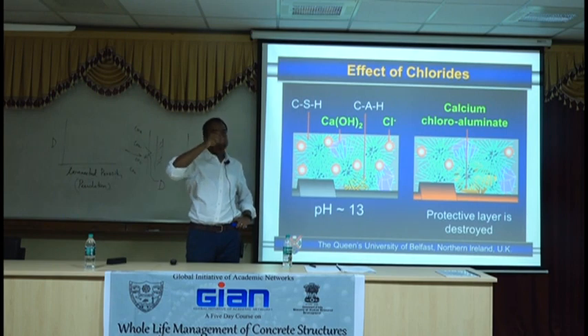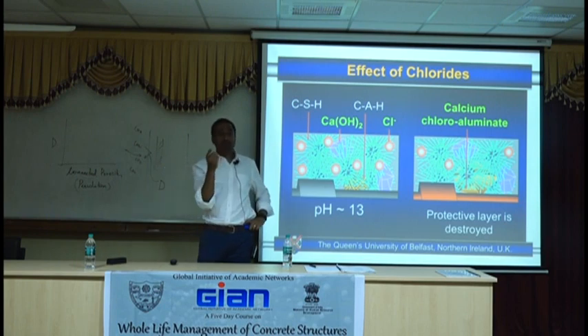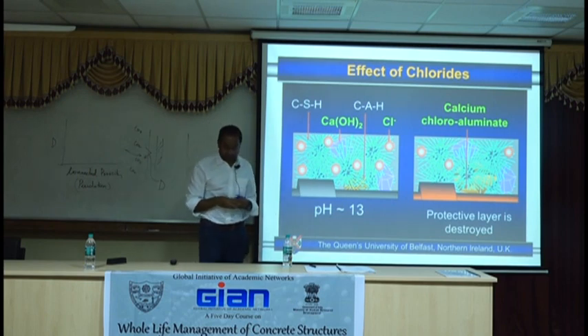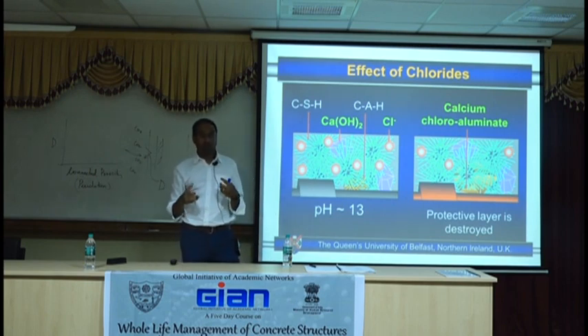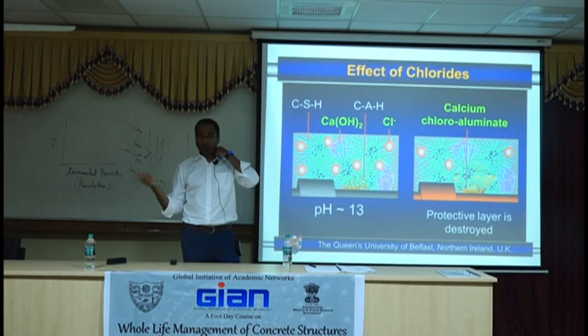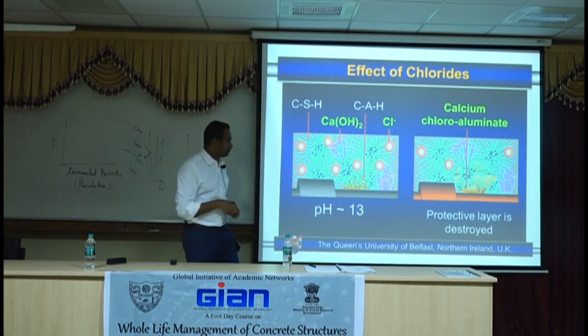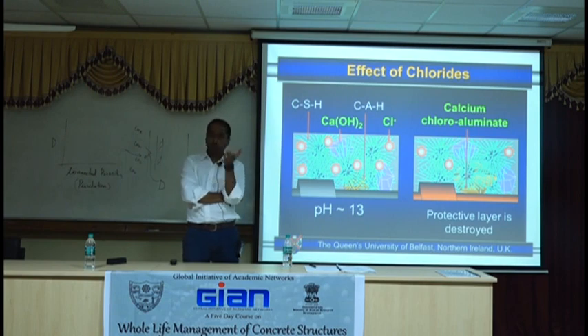Is it a powder that you get or a slurry, microsilica? Because of the health issue with silica in the UK, they prefer slurry. So it's just a liquid form: 50% microsilica and 50% water. So we adjust that with the mixing water. Anyway, that means it's not too far. Meaning you're already practicing it. Not possibly viable for every structure, probably for very typical structures.